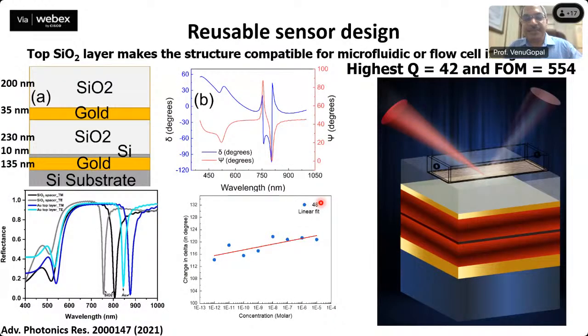We also showed a layered structure with a silicon dioxide layer on the top. Because it's SiO2, which is index matched to a glass cuvette, we can put a flow cell on the top and flow the analyte, and we can do these ellipsometric measurements to get close to single photon level sensitivity in detection of biomolecules. Here I'm showing data up to 100 femtomolar sensitivity. Right?